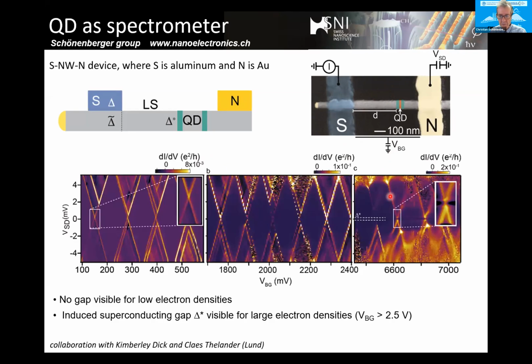So now this is the interesting experiment for this session here. So here we have a quantum dot generated by this crystal phase control in indium arsenide. The superconductor is aluminum, and it's placed on purpose some distance away to study how the gap, or how proximity effect, is evolving in this lead section when you change the doping of the nanowire.